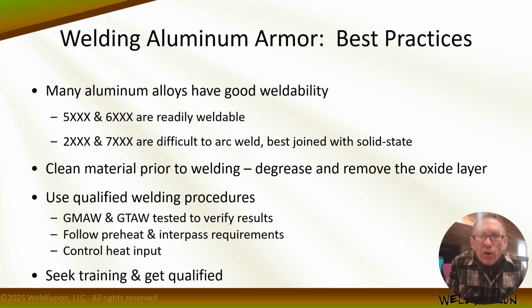You need to clean your material prior to welding. Think about this. That oxide layer melts at 3 times the temperature of the base metal. So that means you're really going to struggle to get good penetration down to the root, especially in a fillet weld, because if you don't clean the material, that's going to resist melting and fusion down in that area and be a potential discontinuity. Right? You need to degrease and remove the oxide layer. Degreasing removes hydrogen, which can lead to porosity, as does removing the oxide layer to get rid of moisture in the surface, and it makes it so that aluminum melts at a lower base metal temperature, right? So that you can get good fusion and get moving quicker without putting in too much heat.